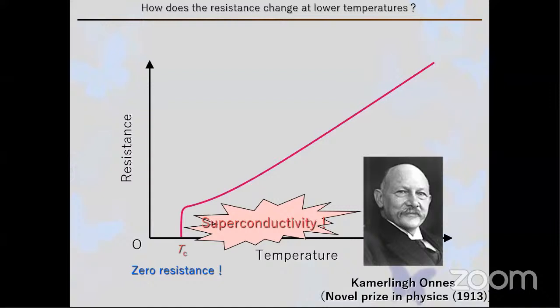So the resistivity becomes nearly zero. He couldn't believe this result, even though he measured it. So then he named it superconductivity. That means the resistivity becomes very, very small, like 2 orders, 3 orders, 5 orders smaller than the usual normal resistivity. They couldn't believe the zero resistivity because that has to happen only around 0 Kelvin. So he named it superconductivity. This is the beginning of the history of superconductivity in the world.